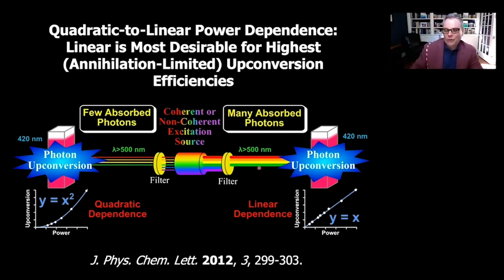But the other way you can do it is you can blast it with laser sources, which is what a lot of people do. Then you can use lower concentrations, but you can still get to the linear power dependence. But on the other side, if you have few absorbed photons, then you're always going to be pinned to this quadratic dependence, which we have very clearly shown you exclusively throughout this whole presentation so far. We were really concerned about doing things at very low power, very low concentration. So this forced us into the quadratic regime all the time.